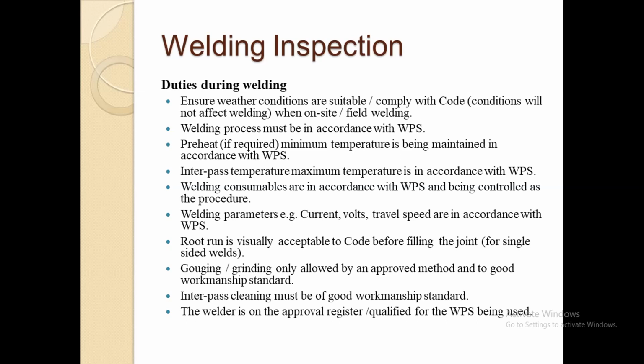The inspector has to ensure that the entire welding process is in accordance with what is specified by the WPS. Remember now, WPS is the document that instructs the workers how the weld is to be done. All right, the preheat has to be checked and make sure that that minimum preheat temperature is maintained. The interpass temperature where specified is to be checked and maintained. The welding consumables are the right ones being used and they are controlled as required. The welding parameters like the current, the voltage, travel speed, etc., are within what is permitted by the WPS.